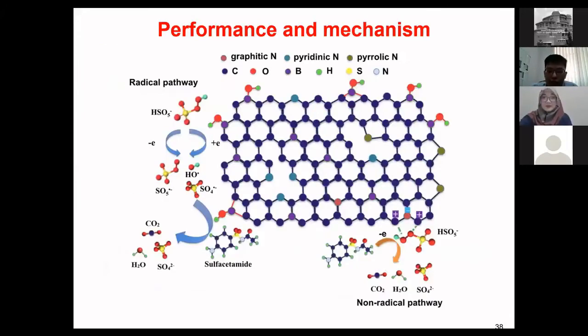Okay, so just to share with you some mechanism, if you have this boron and nitrogen in this configuration, you will have more radical pathway, which means that you can generate a lot of sulfate and hydroxyl radicals for removing pollutant.